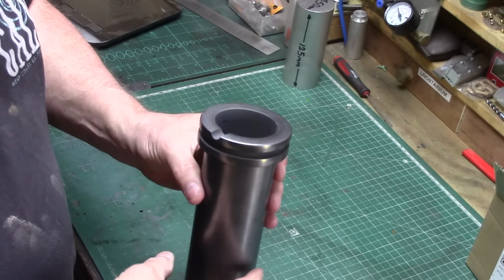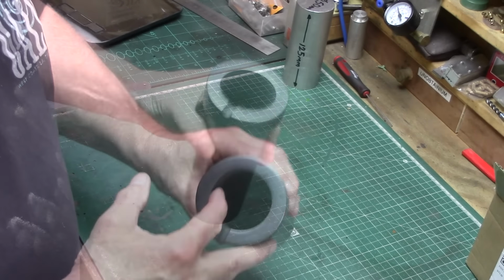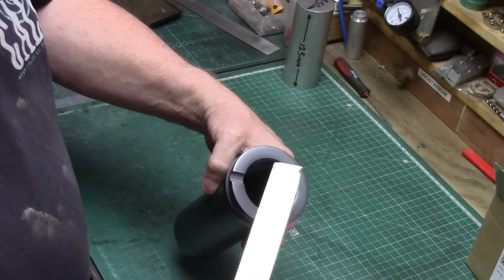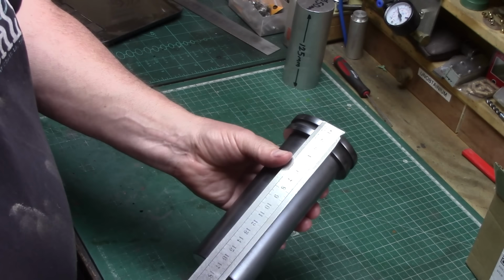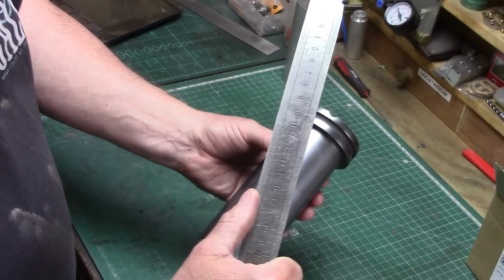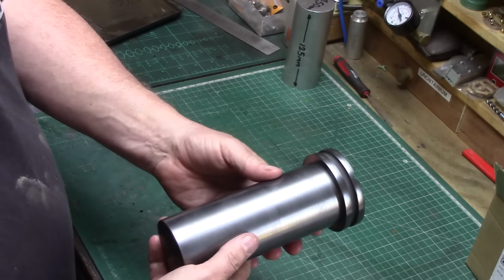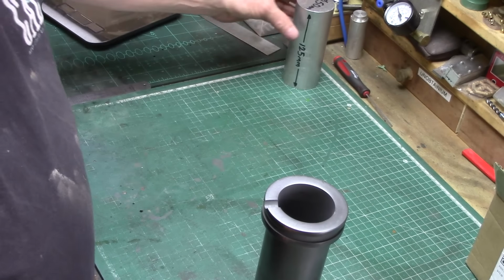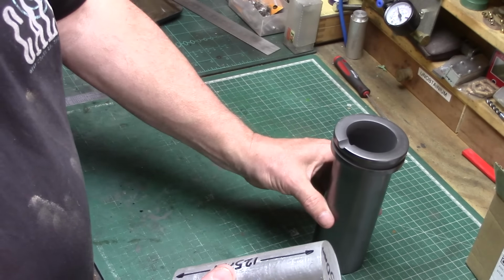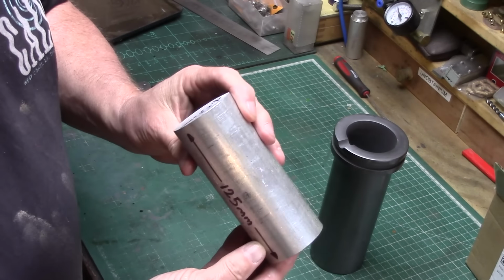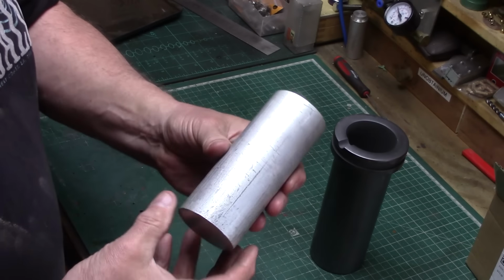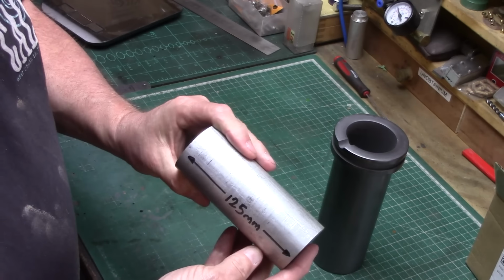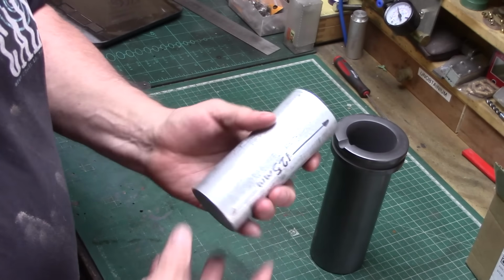Now the crucible is plenty large enough for small engine castings, with a 50mm hole at the top and 170mm in length. The actual volume of metal at 75% full, as recommended by the manufacturer, is approximately 125mm by 50mm diameter, which is actually quite a hefty chunk of metal.